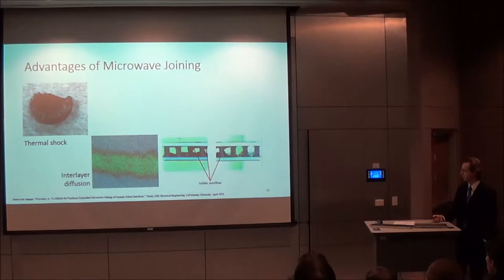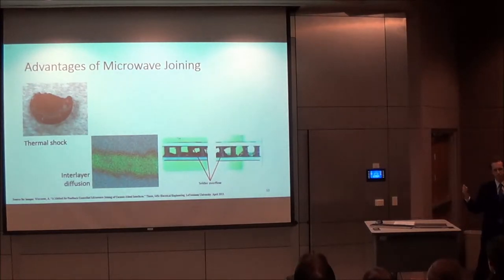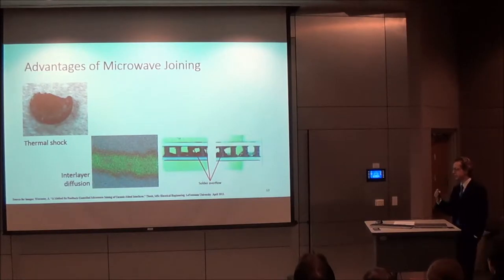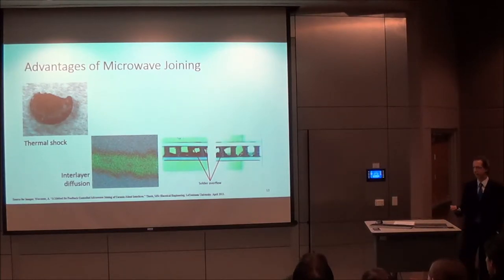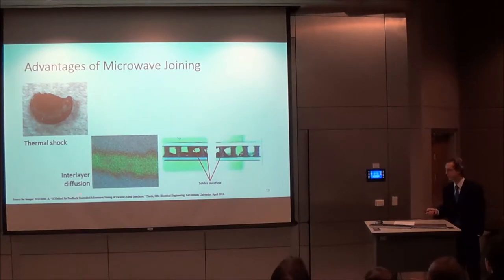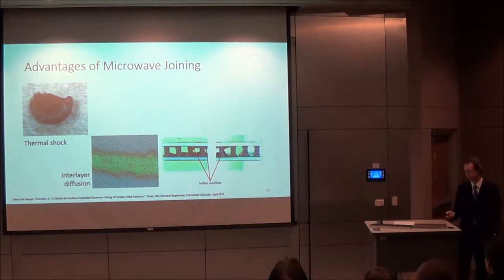develop stresses that can cause failure and cracking. In addition, between the interlayer, between two materials of very dissimilar nature, there tends to be a molecular atomic transport that occurs across the interlayer. And it will often produce intermetallic compounds at the edges of the base materials that will weaken the joint and reduce some of its properties, for instance, the thermal conductivity or electrical conductivity, which are important for the particular application. Also, many traditional processes like furnace-based soldering will apply a lot of heat over a long period of time in order to make sure every joint is made, but in the process, solder can overrun in many of the joints and cause problems that will reduce life.